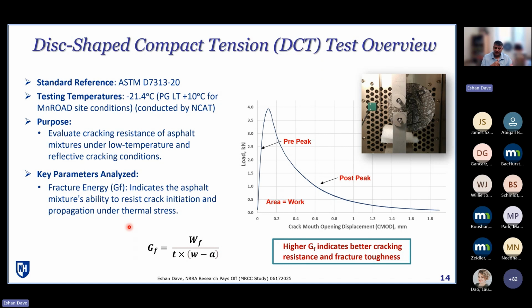and as a result, we need to make sure that these mixes can survive those low temperatures and do not undergo cracking. Just one point that I'll mention is that phase one of the NRRA effort on reflective cracking clearly showed that thermally induced reflective cracking, when you have very low temperatures and, as a result, low fracture energies in asphalt overlays, together with the underlying joint opening because of thermal shrinkage, was a much more severe condition for cracking than the general traffic-induced reflective cracking that you may see at room temperatures or at warmer temperatures. So it is extremely important to look at low temperature characterization of these properties.